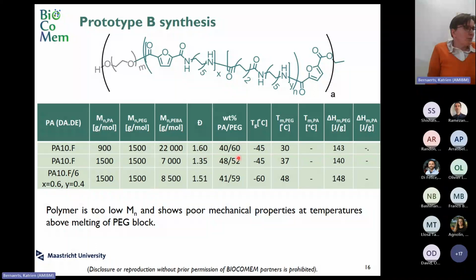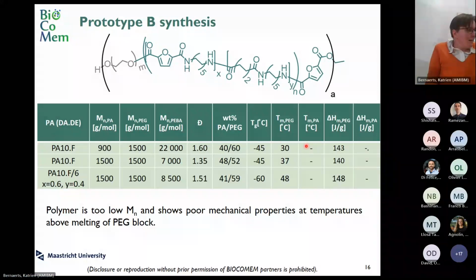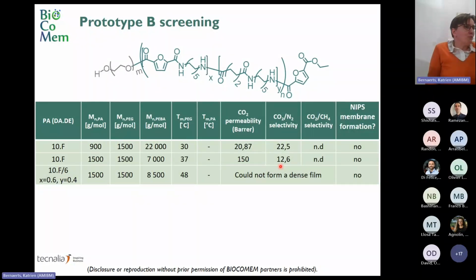If we look further, we see that those polymers are characterized by a low Tg. That's, by the way, the case for all the PEBAs we made. And we only see a melting point for the PEG. So the polyamide part is not, like we targeted, having reduced crystallinity. It's not showing crystallinity. Then we go to the screening, and Oana will explain the slide about the screening results.